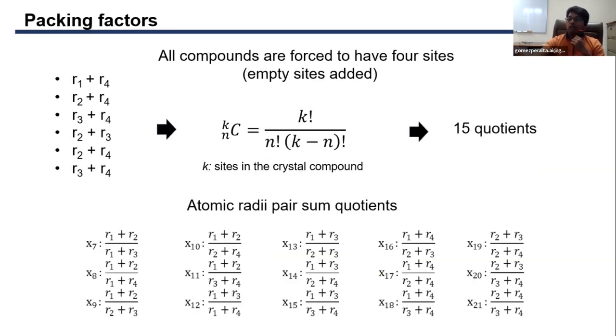Again, in a collection of compounds with up to 4 Wyckoff sites, you can initially obtain 6 combinations of atom pairs for doing addition, 6 different sums. And with these 6 different sums, you can make 15 different combinations to create packing factors, as it is shown now in the slide. In a collection with up to 6 Wyckoff sites, which is not shown currently in the slide, with this strategy, you can obtain 105 packing factors. And I mention a collection of 6 Wyckoff sites because it is the result I will show you later.